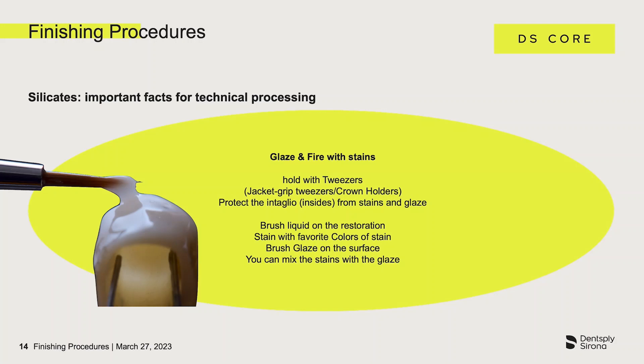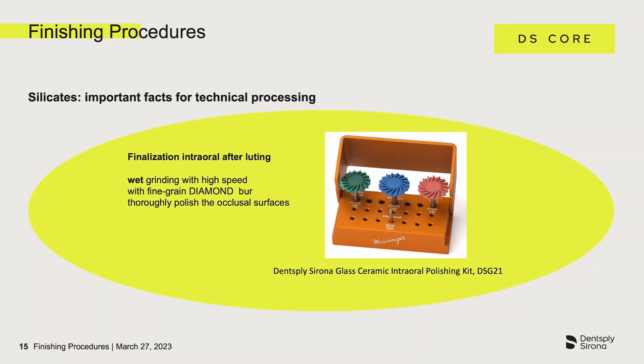The finished glazed crown is fired in the kiln according to the material manufacturer's instructions and firing protocol. If you work with the speed fire kiln, the protocol for each material is saved and predefined. After adhesive luting has been completed, it is important to ensure that intraoral finishing is carried out under good water cooling with less contact pressure. Any interfering contacts should be ground with a fine grained diamond, and any area processed with the diamond should also be polished to a high gloss again using silicone polishers in descending grain size.